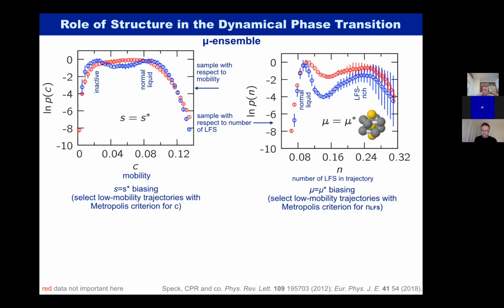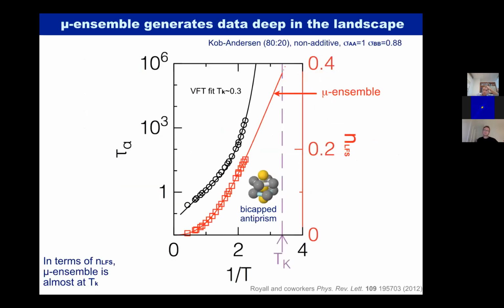So in the blue data on the right-hand side, there's the normal liquid at low numbers of local structure, which I denote as N, and at high numbers of local structures, there is an additional peak, an additional dynamical phase that we discovered. What does this mean? Well, we are now able to generate configurations that have really large numbers of local structures in them. We call our method the mu ensemble.